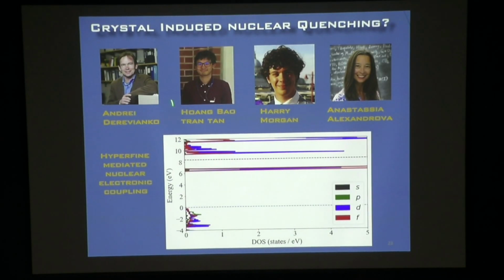And so what we got worried about was that, and I should say we worked with Andrei Derevianko, who's amazing, and his postdoc Bao, we started thinking about how the hyperfine interaction between the electrons and the nuclei could couple the two degrees of freedom and could potentially lead to this quenching. There are many ways that this could happen, but generically, it's something like this. Suppose I have an excited nucleus. It's about this much energy. If it's coupled to the electrons, it could give energy to them. And it could resonantly excite an electron down here, it needs to be a thorium-centered electron to really talk to it, up into this defect state.